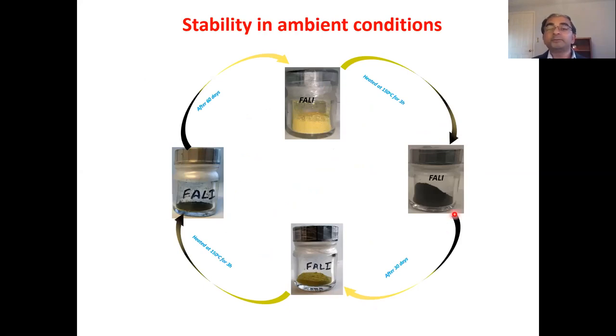But when I put this black phase for 30 days in an open environment, it converts into light yellow. This is not a pure perovskite. When you do XRD, you will get some other peaks also. But when I again heat it at 150 degrees, I again get a black phase. And when I put it for 60 days, I get a pure yellow phase. This means that